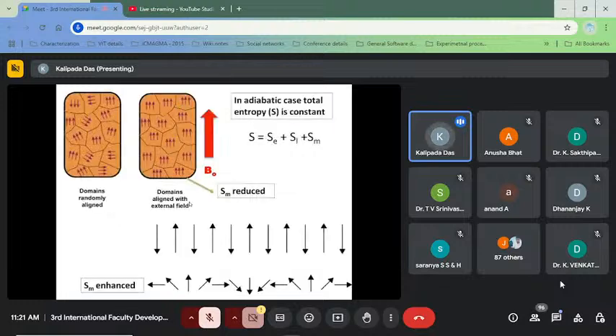Now, this is the basic idea behind the magnetocaloric effect. The magnetocaloric effect is associated with the magnetic entropy change of a material when it is placed in an external magnetic field. Generally, when the magnetic field is absent, the domains are randomly oriented, but when the magnetic field is present, the domains are oriented along the applied field direction. If we apply the magnetic field adiabatically, then in the adiabatic case the total entropy of the system is constant. That is the electronic part, lattice part, and magnetic part. The sum of these three terms should be constant.